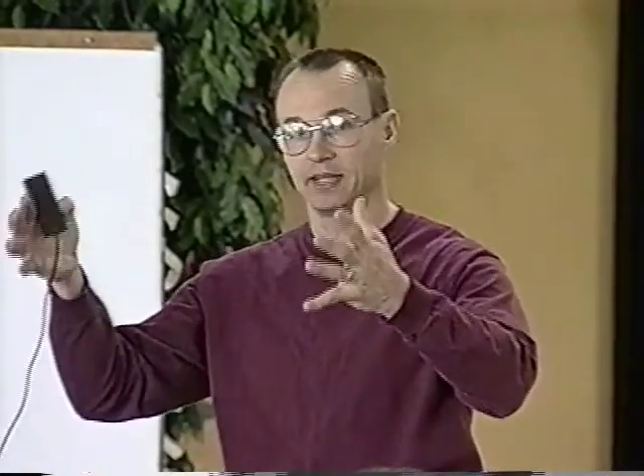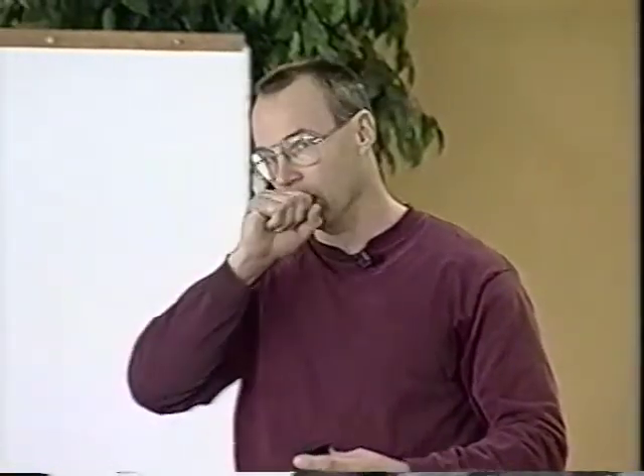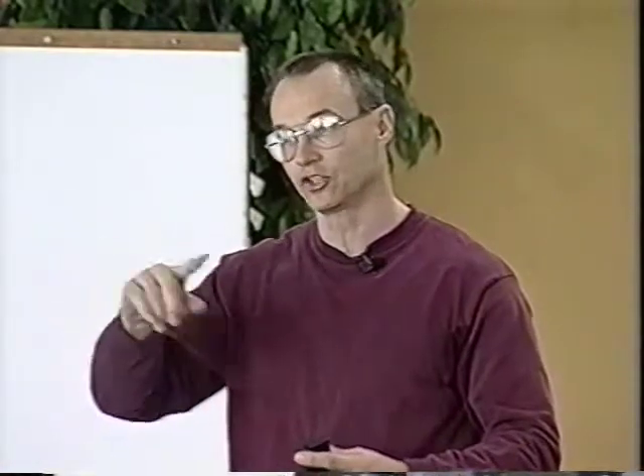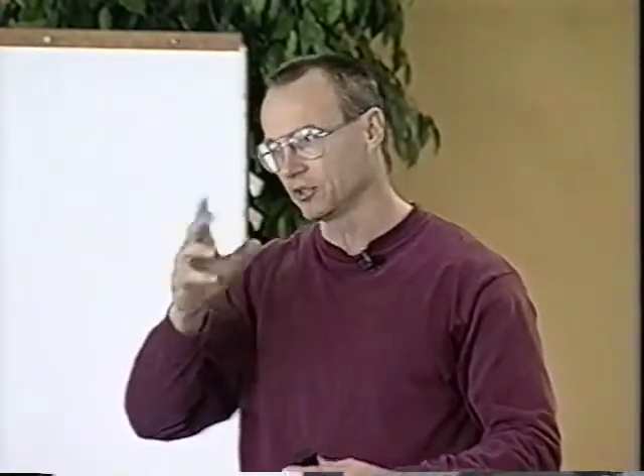And the big thing about casting is most of our strip grades are compatible, if you will, chemistry-wise. You got to remember that 300-ton ladle has got a chemistry of its own. And I bring in a new 300-ton ladle, the chemistry of it might be for another customer, and it might be slightly different. So I'm going to get a steel mix inside my tundish because I am constantly pouring steel. So we might lose a couple of slabs in the process, those 2 slabs coming out of either end where I had the chemistry mix.